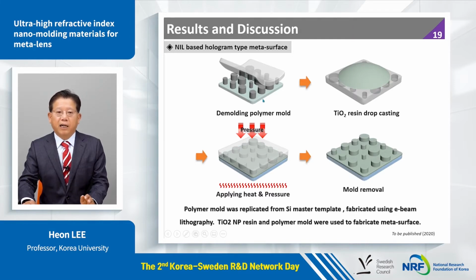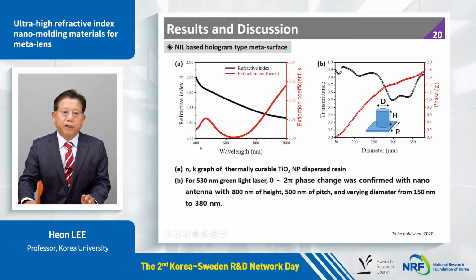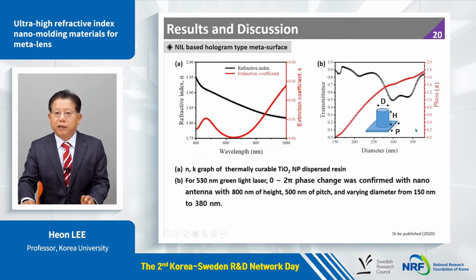This is another example. I have a master mold, and from this master mold, I can replicate the polymer template. On the polymer template, I coat the titanium oxide resin, then do imprinting, and finally we have a metasurface. If I have one master, I can make millions of metasurfaces using the imprint lithography process. When changing the diameter of each nanocylinder, we can change its phase from 0 to 2π by adjusting the diameter from 150 to 380 nanometers. It has a quite low k value and also a high n value, so it's very suitable material for lens applications.